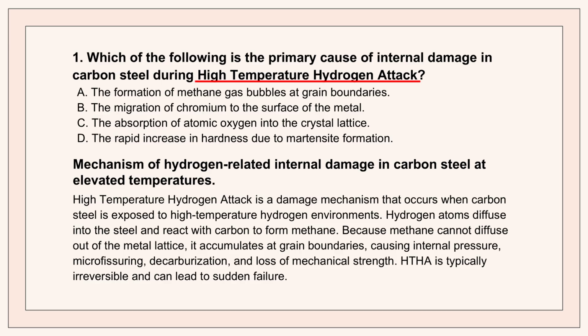The key insight is that the primary internal damage is caused by the formation of methane gas bubbles at grain boundaries. That's it. That is the whole story right there. You have hydrogen gas that diffuses into carbon steel at high temperatures. Once it's inside, that hydrogen reacts with the carbon that's already in the steel, the very thing giving it strength, and it forms methane gas.